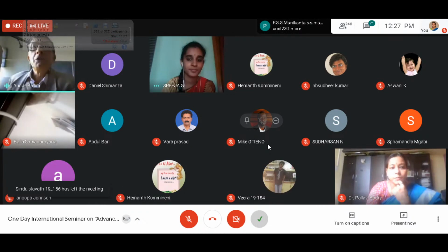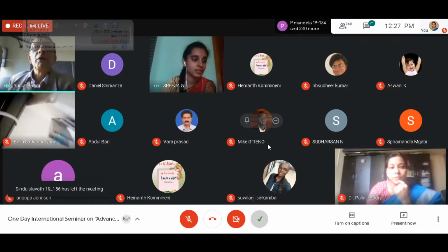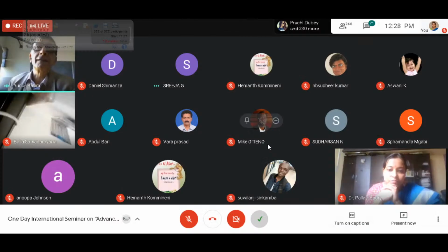If I understand the question, what about the effects of different pozzolanic materials? Yes, sir. We've tested fly ash, and slag is not a pozzolan, but we've tested slag as a latent hydraulic material. And as you saw, I showed you results for condensed silica fume, which of course has no influence in reducing heat rates.